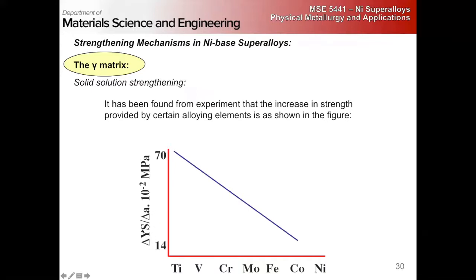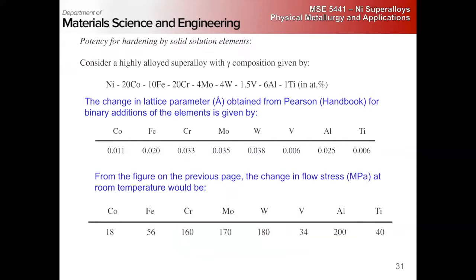Okay, so in the gamma matrix itself, we are primarily adding alloys for solid solution strengthening, right? And this basically just shows you for different elements a schematic of the increment in yield strength due to them being in solid solution, right? And there's some empirical relationships that you can use to determine the effect of strengthening as a function of the alloy composition, right? And if we remember back to the very beginning, we know we have 2 main effects for solid solution strengthening, right? We have a lattice mismatch, lattice size effect, and we also have a modulus effect.